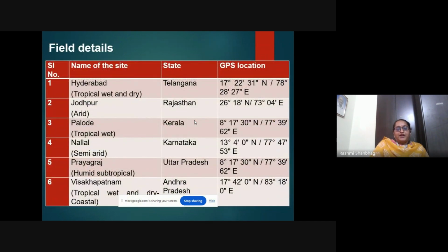For our study, we selected field trials at Hyderabad, which is tropical wet and dry, Jodhpur, which is the arid region, Palode, tropical wet, Nallal, which falls under semi-arid conditions, Prayagraj, humid subtropical, and Visakhapatnam, where we did it in tropical wet and dry condition, but again coastal. Other than that, we also did it in the highland, but those results are not shared here, as those studies are still continuing, and till this level we could not get the result.